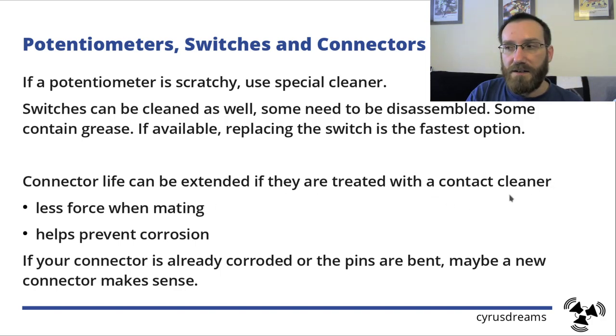And I've never had a case where contact cleaner was not compatible with the plastic of the connector, and that oil is non-corrosive. If your connector is already corroded or the pins are bent, you can bend them back, but they might have lost their springiness with repeated bending. Corrosion most of the time will remove the coating that the connectors have, so the tin or gold coating, and the copper or ferric metal base of the connector pin is not protected against new corrosion anymore, so it will corrode all the time in short time.